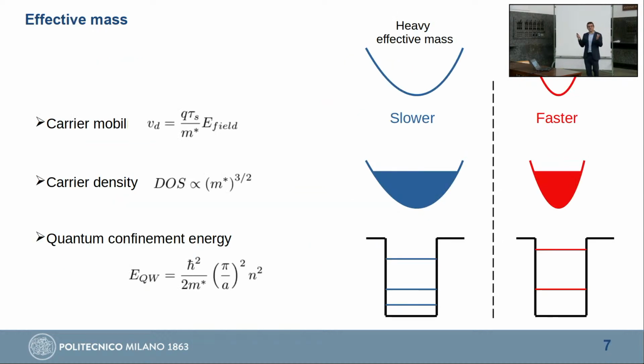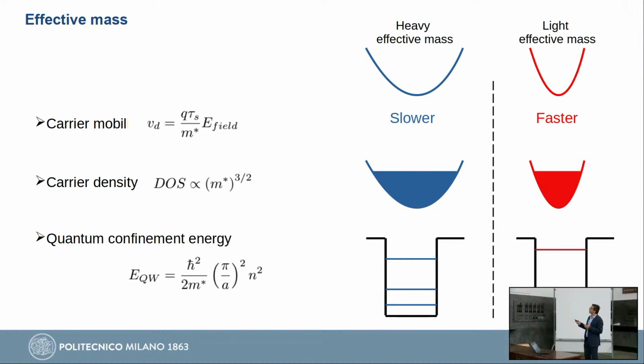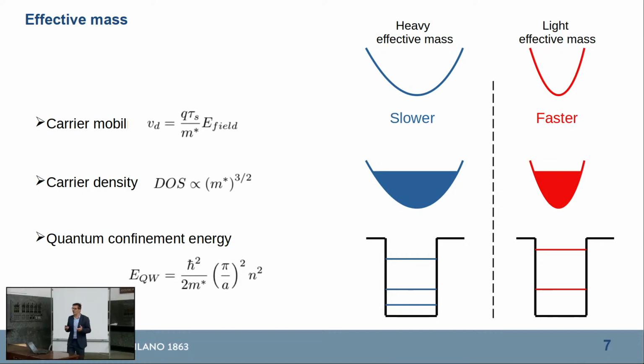So for example, we can define two broad cases where we have a heavy effective mass, which means that we have a very small curvature here, or a light effective mass when this is a larger curvature. And for example, the effective mass enters in determining the carrier mobility. So how fast an electron or a hole move in a semiconductor. And this is ultimately one of the parameters telling us how fast a transistor can behave. So if the carriers are slow, I will never reach a transistor with a gigahertz operation. And so typically, if the effective mass is lighter, I will have a faster carrier and a faster device.